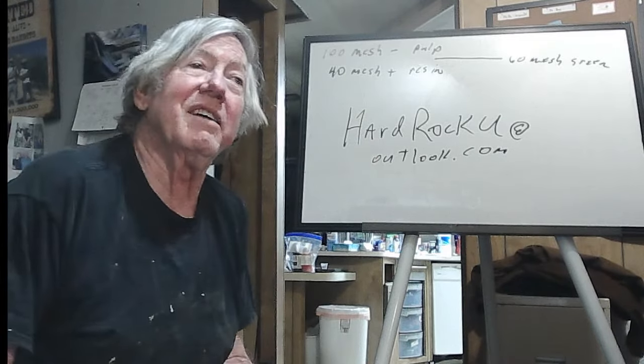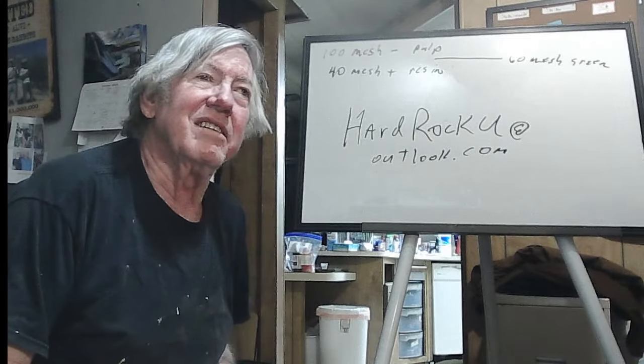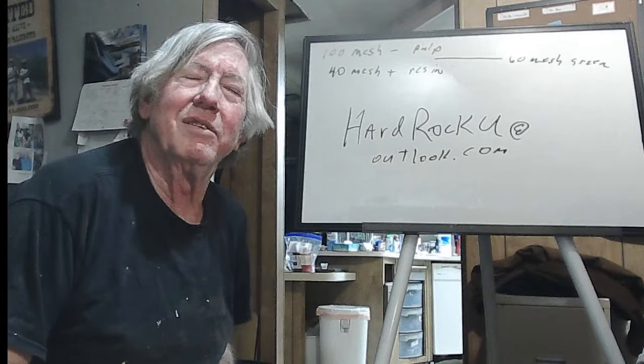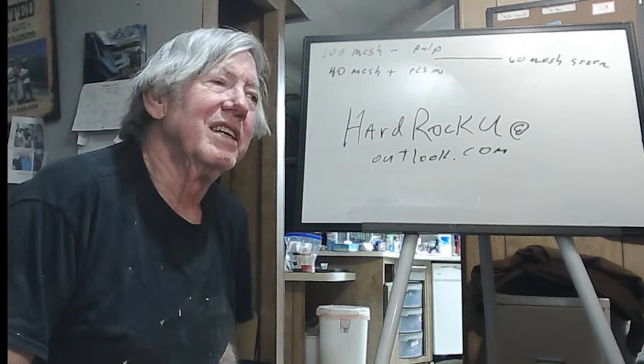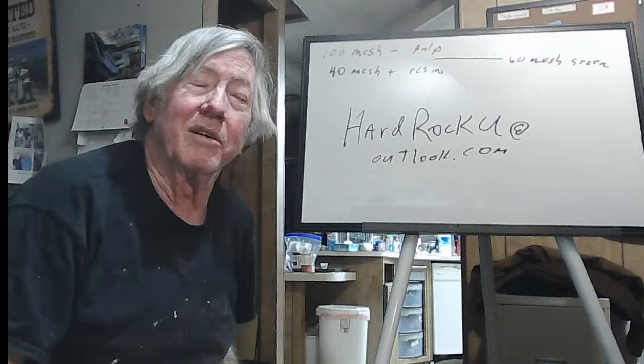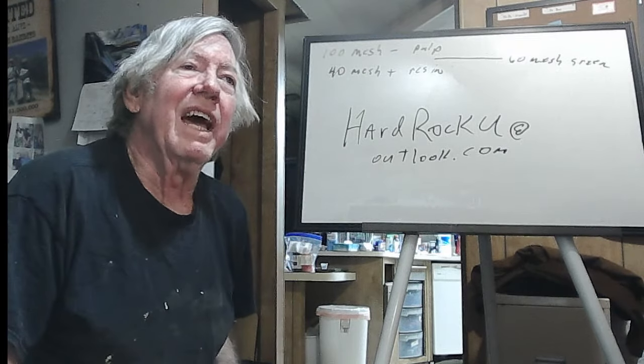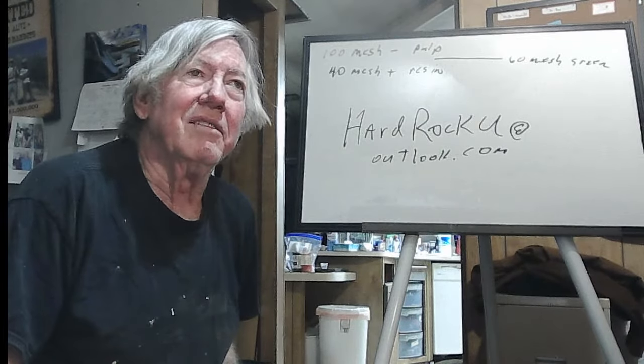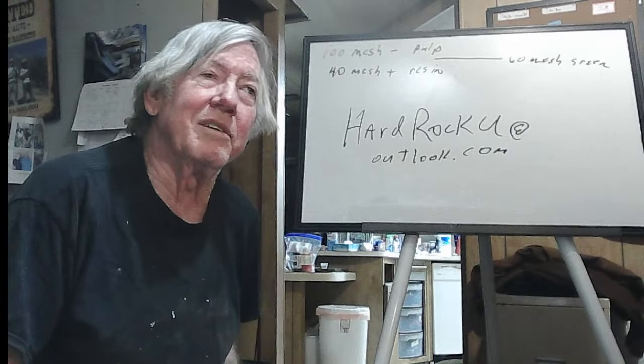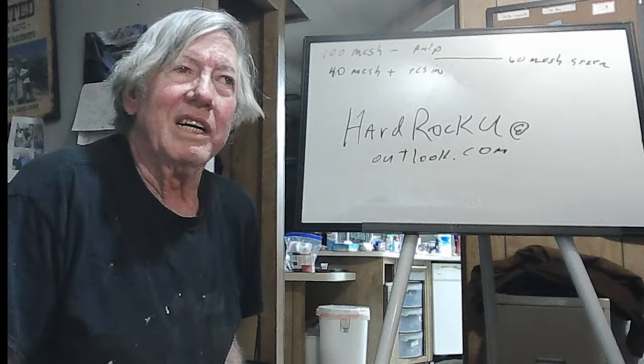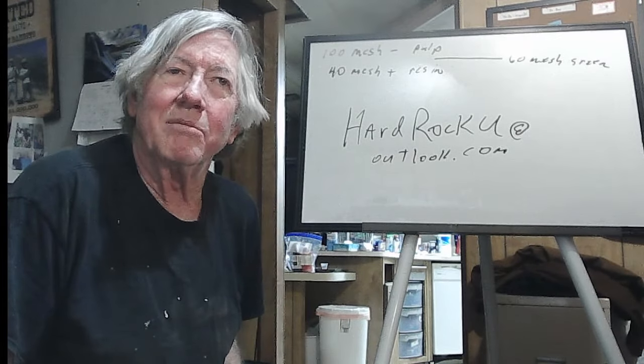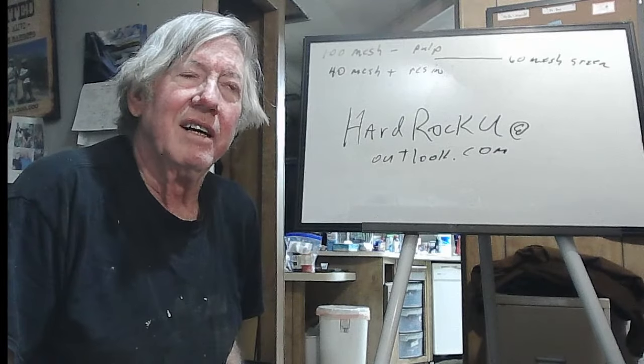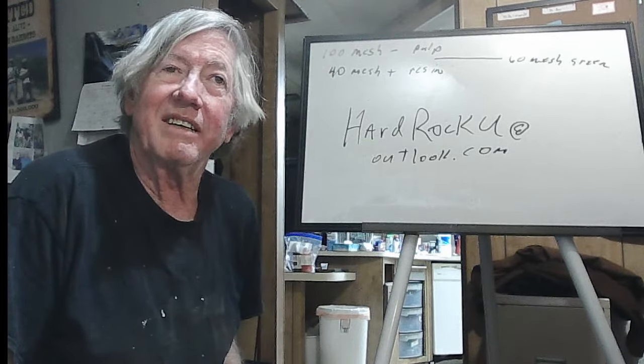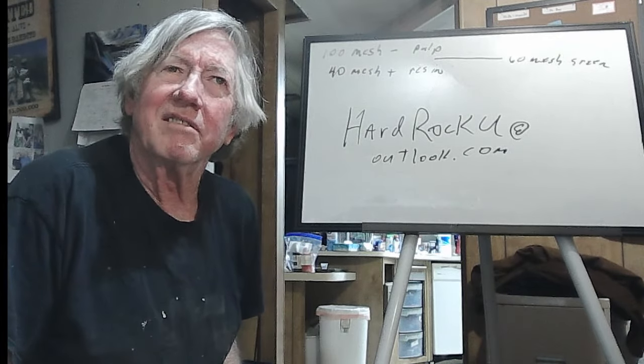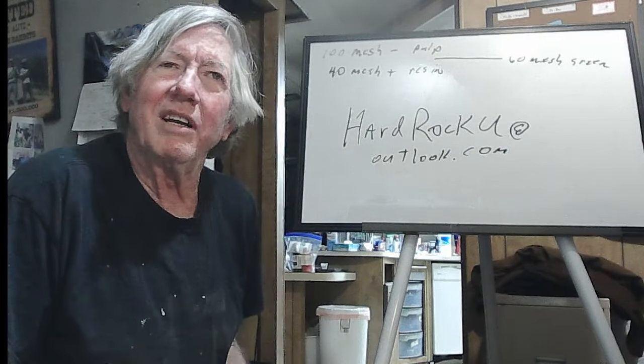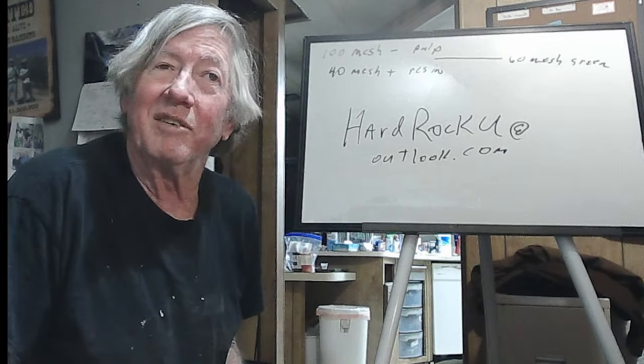Okay, well, what I did was I went back to the lab, and I tested the remaining amount of the pregnant solution that I used, and it was running 11,800 parts per million total dissolved solids according to the meter. And the barren solution was running about 11,400 parts per million dissolved solids, which, when you do the math, works out to about 0.2 grams of stuff missing, which should have pretty well loaded that resin.